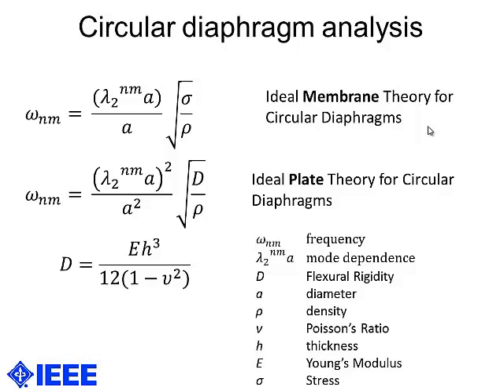We also wanted to consider that due to the very high Young's modulus of the diamond, it might act more like a plate. So in the plate equation, we have a dependence on the flexural rigidity, which is dependent on Young's modulus, thickness, and Poisson's ratio.